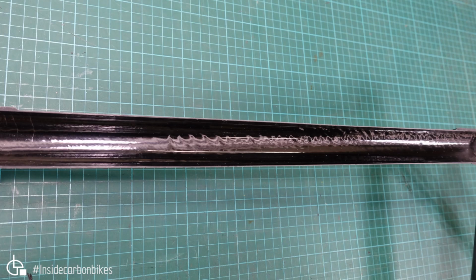Overall, the top tube, you can see a little bit of fiber distortion, you can see all of it down here, where the pressure's probably not quite even, a little bit resin rich. As I said before, for some reason the top tubes seem to be a little bit more susceptible to damage than other tubes on the frame, so they could be a little bit resin rich, which would do that. It would be interesting to do a resin burn off and see what the fiber volume content is. If it is resin rich and it's not a toughened resin, then that would probably make the tube more susceptible to damage.